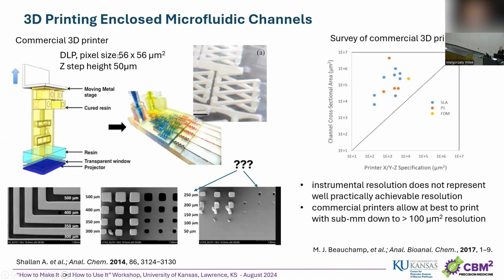And as we're talking about the resolution, we look at the specific commercial 3D printer, which was DLP type with a relatively large pixel size, 56 by 56 micrometers, and Z-step height of 50 microns. So you would assume that making channels on this order of magnitude would be, okay, that's what's mechanically possible, right? But when these researchers did their studies, the smallest channel that was still open after the processing was actually on the order of 250 microns, right? So much larger than what's theoretically possible with this equipment.